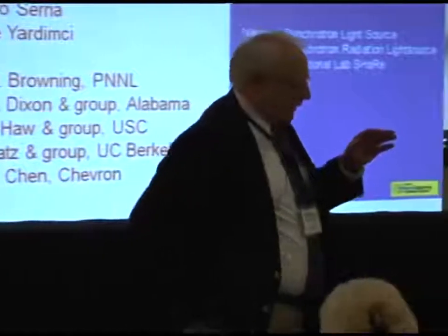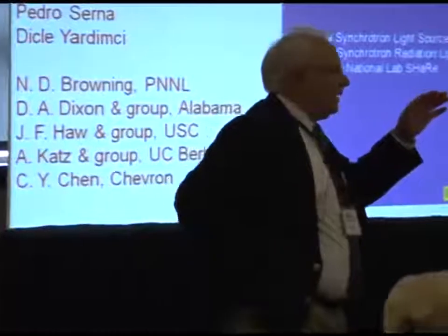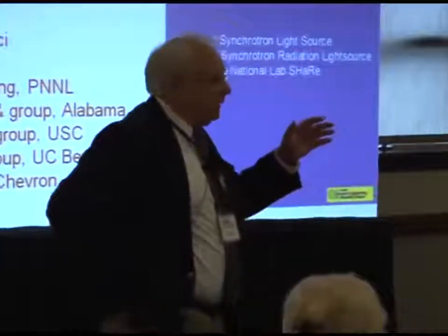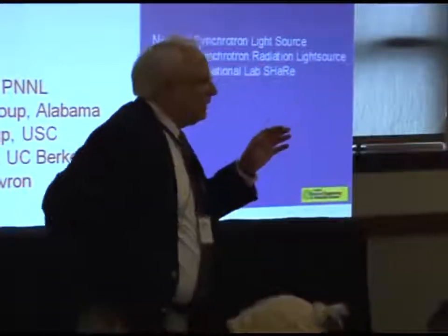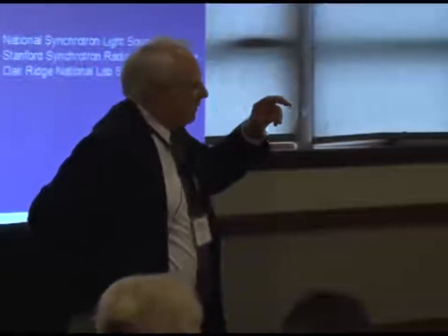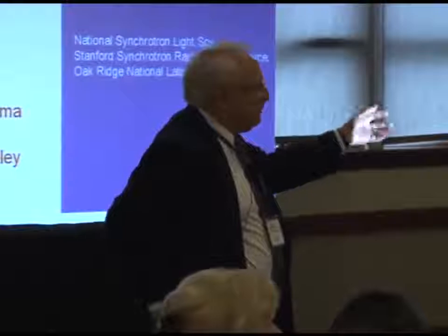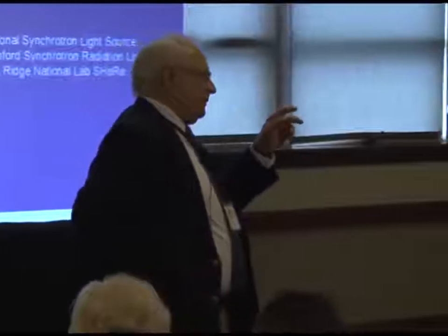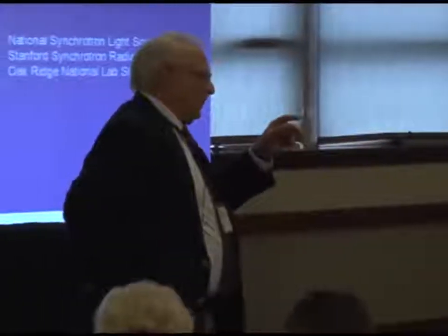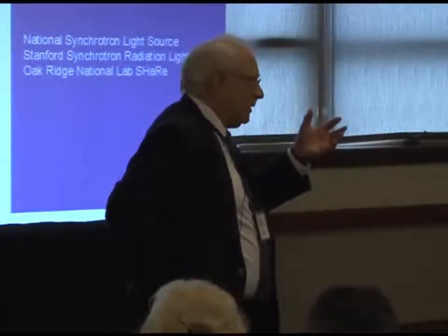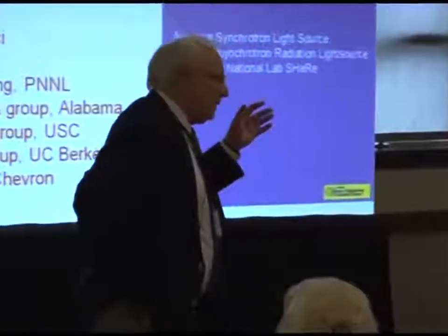So the first thing I should say is that we've done experiments with other metals than these. And if we go left in the periodic table to more oxophilic metals, rhenium specifically, then we get a big boost in stability of the cluster. So we can go to 400 degrees or something doing hydrocarbon conversion with the supported rhenium clusters, they're trirhenium. If we now move to the right in the metals I talked about, then we've got less stability because, at least in a reducing atmosphere, the noble metals have a strong tendency to be reduced and aggregated, sintered, if you want. So we've run these under mild conditions to avoid that.